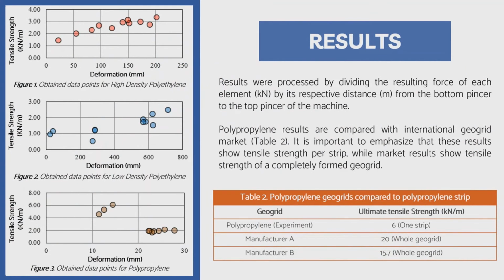Experimental results. Results were processed by dividing the resulting force of each element in kilonewtons by its respective distance in meters, from the bottom pincer to the top pincer of the machine. Maximum tensile strength achieved per material are shown in Table 2. Polypropylene samples achieve a maximum tensile strength of 6.08 kilonewtons per meter. Results are presented in figures 1 to 3.